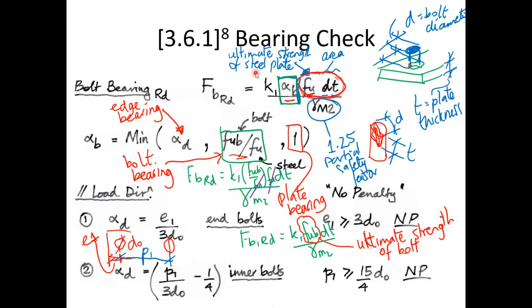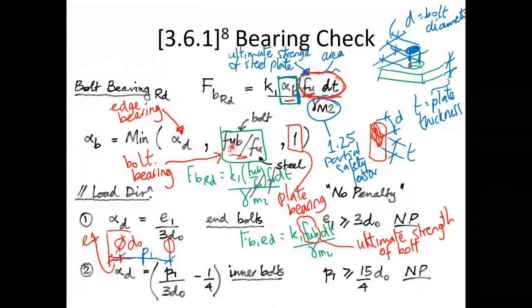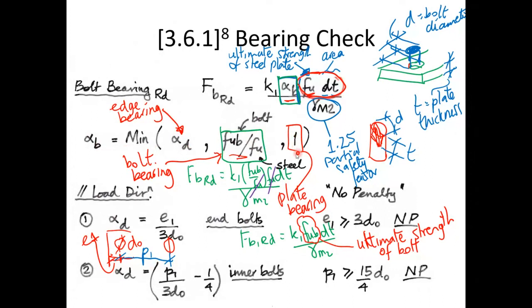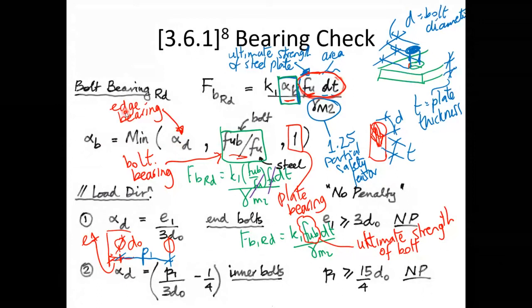Right, so the other thing that we have in that formula for the bearing checks is the factor K1. We talked about what alpha B means. Basically, if alpha B is equal to 1, we're checking for plate bearing. If alpha B is equal to FUB over FU, we're talking about bolt bearing. And if alpha B is equal to alpha D, then that's the edge bearing. Then alpha B is equal to the minimum of those three. In other words, whichever is the smallest of the three is the type of failure that's going to happen first. So if alpha B is determined by 1, plate bearing happens before bolt bearing or edge bearing. However, if alpha B ends up equal to FUB over FU because that's the smallest value, then bolt bearing happens first. Or if alpha B equals alpha D because that's the smallest, then edge bearing happens first.